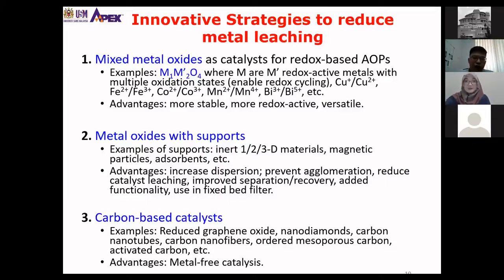So the second approach is to use metal oxide with support, which means that you decorate the active catalyst on the support. So if you do this by decorating the catalyst on the support, you can actually have the function of the support itself. Let's say if you look into decorating cobalt oxide on magnetic particles, which means the overall catalyst will have magnetic properties which can be used to be separated through magnetic separation. Other advantage of using metal oxide with support is that you can increase the dispersion of the catalyst, you can prevent agglomeration, and you can also reduce catalyst leaching through improved interaction between the catalyst and the support.